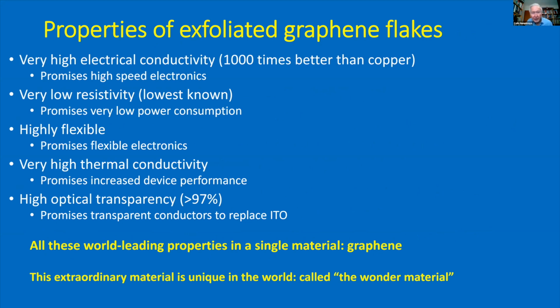So exfoliated graphene flakes, the Nobel Prize winners found graphene has extremely high electrical conductivity. They said 1,000 times better than copper. Because of this, very low resistivity, and therefore that's the reason graphene promises very low power consumption, lower than silicon. Graphene is also very flexible. It has very high thermal conductivity, so it promises increased device performance, because a lot of devices have their performance limited by the temperature at which they run.